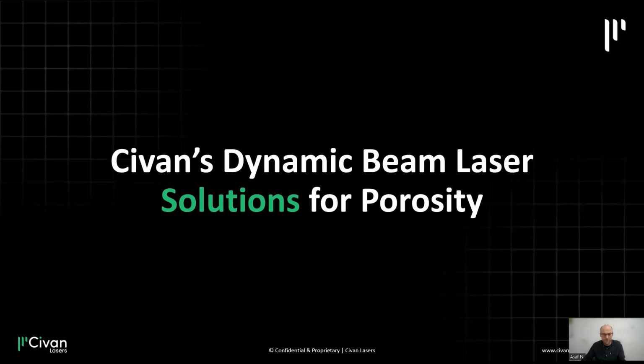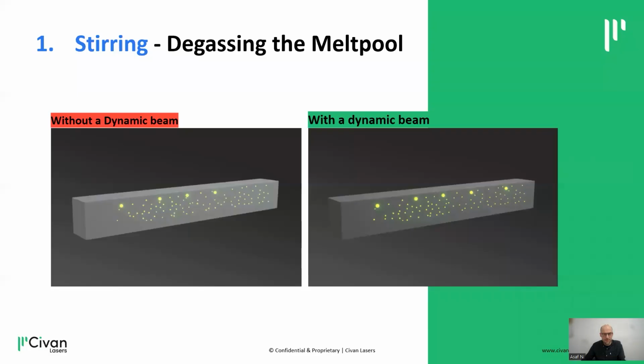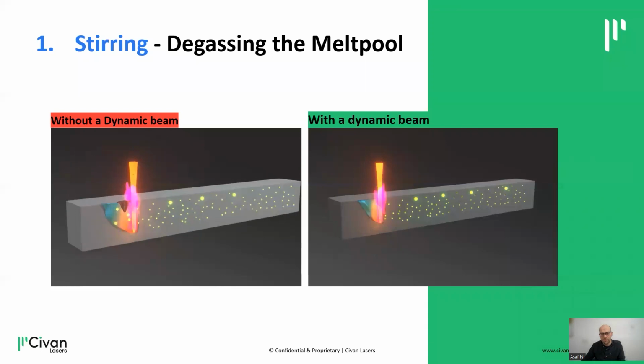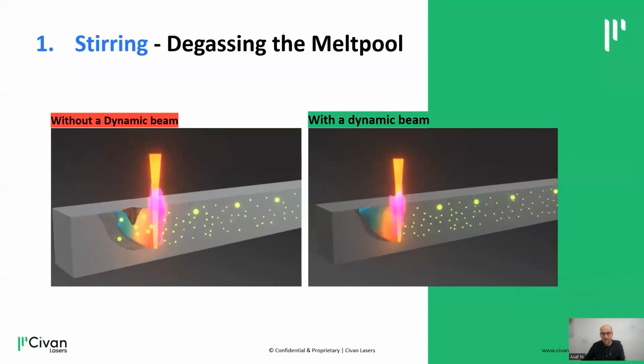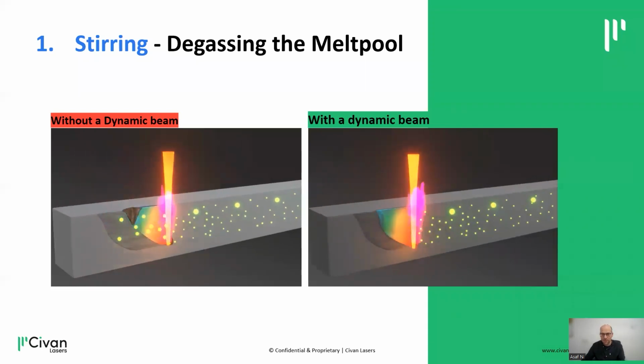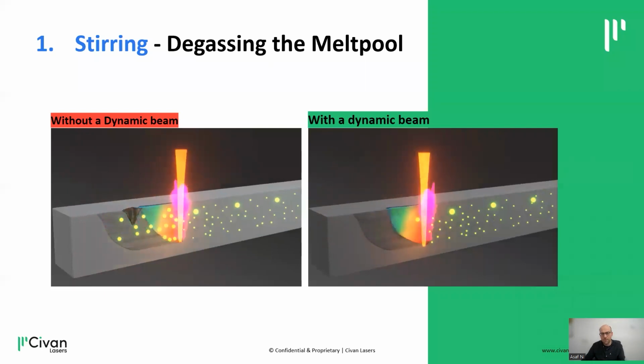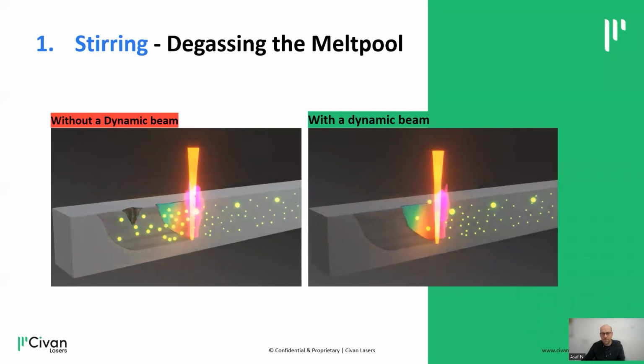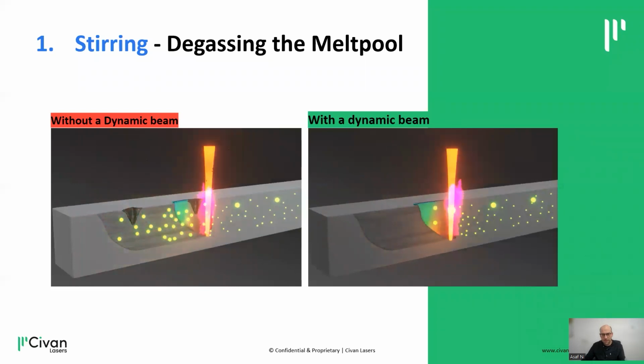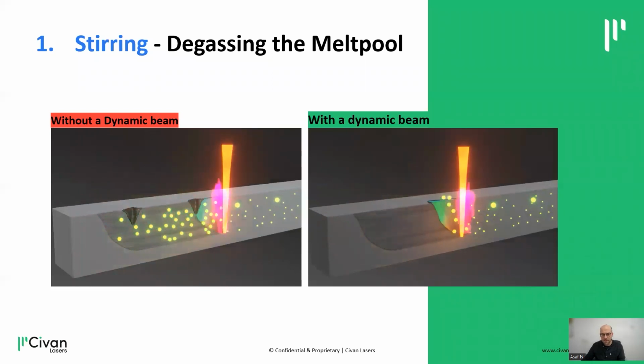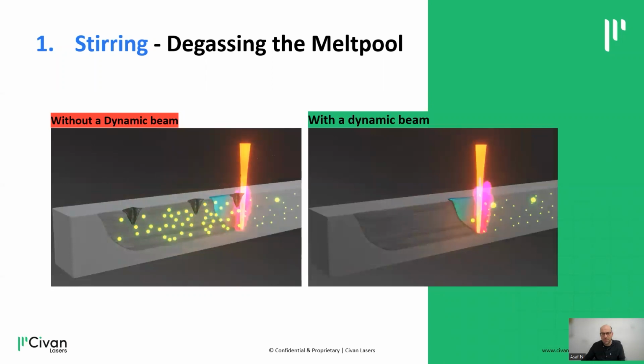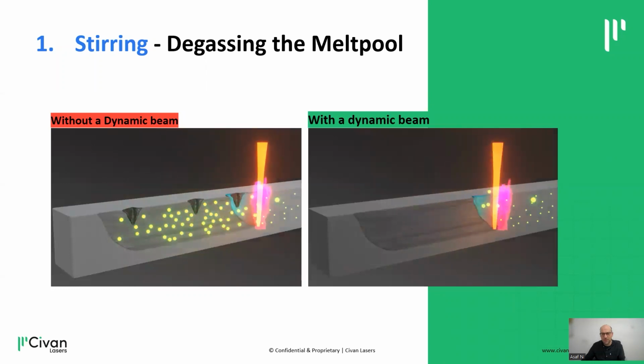So how do we achieve it? The first solution would be stirring. Stirring will induce degassing of the melt pool, such that more gas will come out of the melt. The flow dynamics of the melt pool are crucial to drive more gas out of the melt pool. The ability to design a stirring pattern, and to perform it at a very high frequency, allows improved removal of the gas pores from the melt pool. In the simplified illustrations, you can see a comparison between processes that are conducted with a dynamic beam and without a dynamic beam.